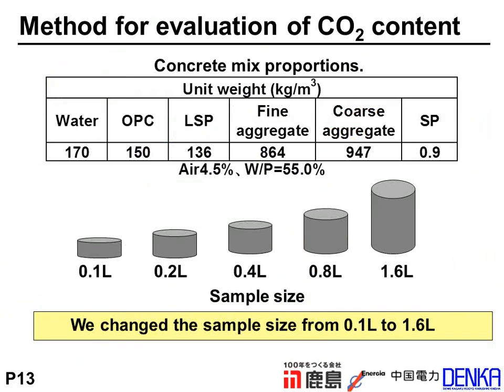In this test, we use this mixed proportion. We use limestone powder as the carbon dioxide containing substance, and we replaced it into ordinary Portland cement. And we change the sample volume from 0.1 liter to 1.6 liter, and we measure the carbon dioxide content in the concrete specimen.